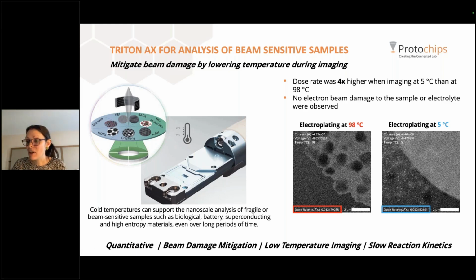Let me touch on the software and some of the software management that's working with it as well. What we've noticed too during those experiments using our dose software was that between the heating and the cooling temperatures, at the cooler temperatures, we were actually able to increase the dose. I don't know if you're able to see, but we are able to increase the dose up to 4 times that than what we were able to do at the higher temperatures.